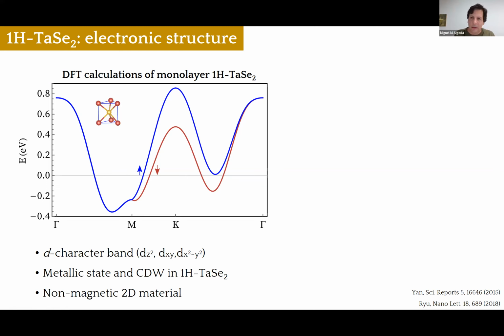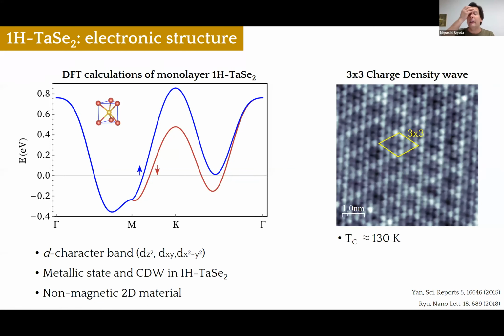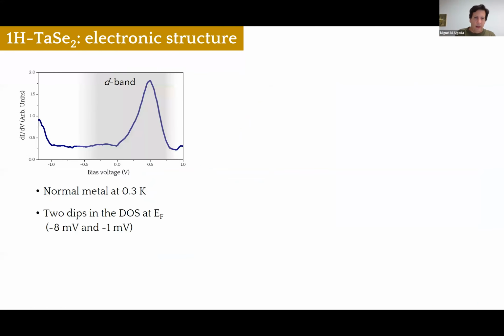And another characteristic of this material in the single layer is that it holds a charge density wave order below 130 Kelvin, in which the STM is very good at detecting these charge density waves, because in addition to the atomic registry, you can see a clear 3x3 pattern that corresponds to the charge density wave. Okay, so here I show you a dI/dV curve taken.